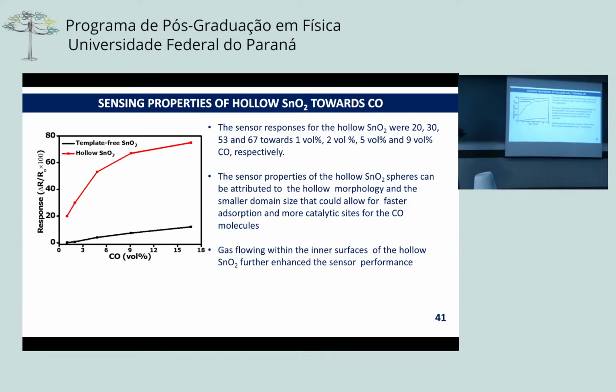So for this one, we really were not successful. We wanted to look into very small ppms, but we couldn't. We only managed to detect carbon monoxide at 10,000 ppm. So that means we could only tell the difference between the template free and the hollow tin oxide. Of course, the hollow tin oxide exhibited 6 times higher response towards 1 volume percent of carbon monoxide as compared to the template free. So this work showed that there is potential, but we need to do more.